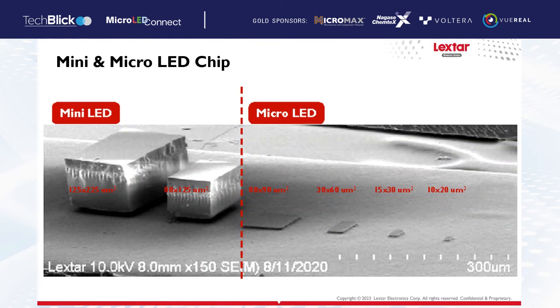What's the difference between mini-LED and micro-LED? You can see in this picture — the left side is mini-LED, the right side is micro-LED. One biggest difference is that mini-LED has an epitaxy substrate, but micro-LED does not. The second difference is size: mini-LED is always around or bigger than 100 µm, but micro-LED is always less than 100 µm. After removing the epitaxy substrate, the micro-LED chip can be shrunk to a very small size, for example 10 by 20 µm. By this micro-LED technology, we can give the display a new era.